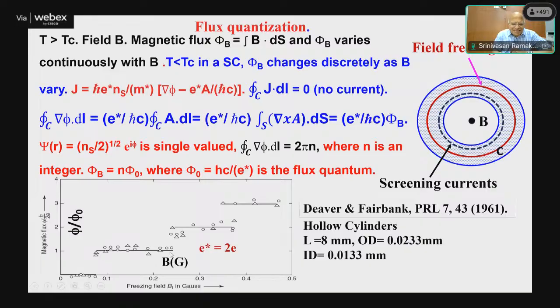This is how you see. You vary the field up to something like 0.25 Gauss, it jumps to the next state, then it jumps to the other state. So it clearly showed that the flux inside cannot take an arbitrary value. It can only take phi b is n phi naught, where n is an integer. So it can take quantized steps.